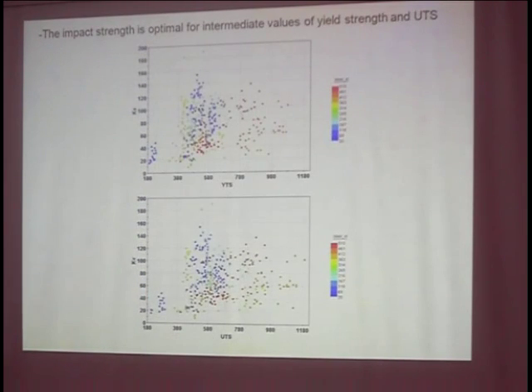The number of welding passes is strongly important in the weld's behavior because the thermal history of the material and the transformation history are strongly related to the number of passes and to the heat input at each pass. The impact strength we found is optimal for intermediate values of yield strength and ultimate tensile strength. This means that if you need very high tensile properties, you do not have such optimal values in terms of impact strength.